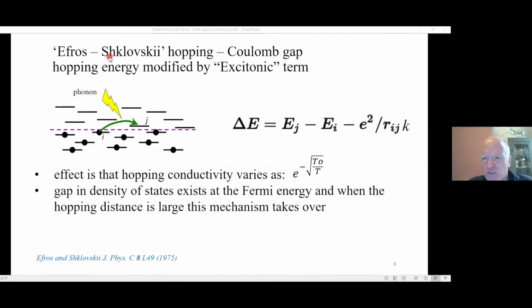The Efros-Shklovskii mechanism is very interesting. When we get into this region at low temperatures and low carrier densities, the transport of charge through the system is by hopping. This is a schematic. This is a state here. The electron or hole hops into a vacant state. It's phonon-assisted.